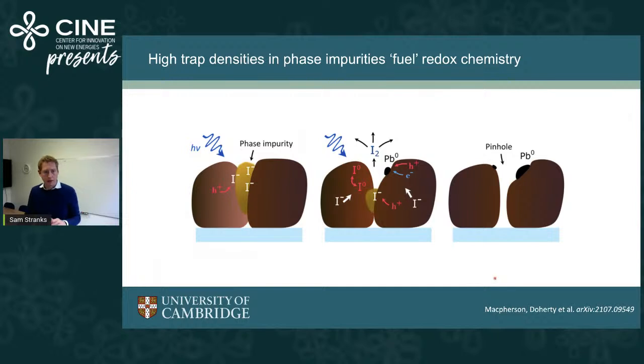So just to bring that together, what's the kind of overall mechanism? So we have this phase impurity sitting at a boundary between two perovskite grains, for example. These act as hole traps, so we have lots of interstitial iodine here, which traps holes. So it's the act of trapping carriers that actually starts catalyzing and starts fueling this redox chemistry. And when we trap holes, we start to form atomic iodine, which then combines to form molecular iodine, which then leaves the system. And meanwhile, we also have photoexcited electrons reducing lead 2+ to lead 0, and we form